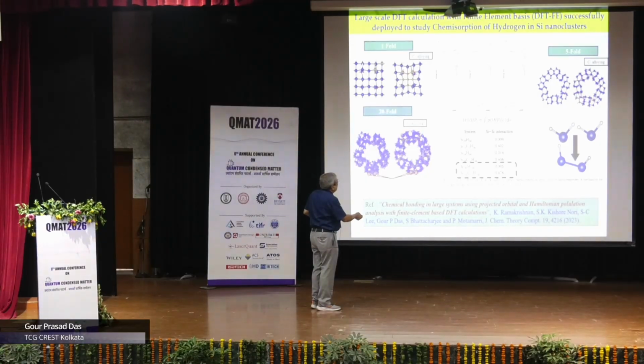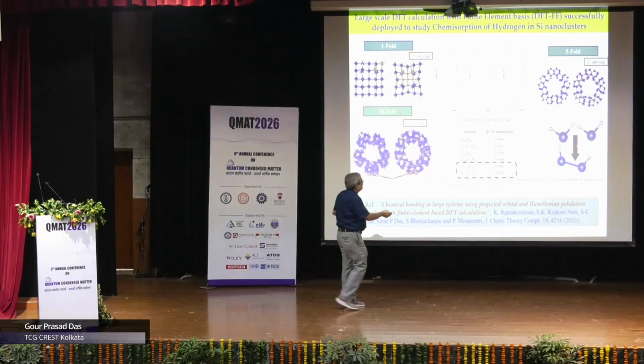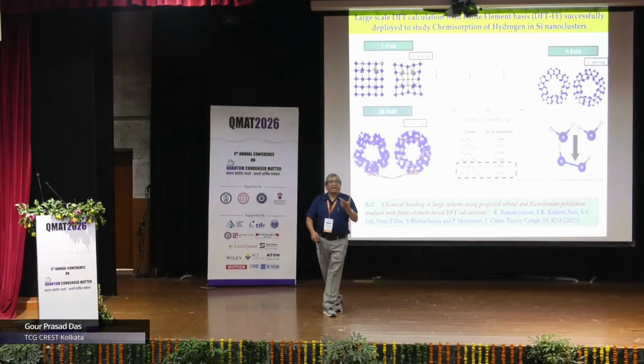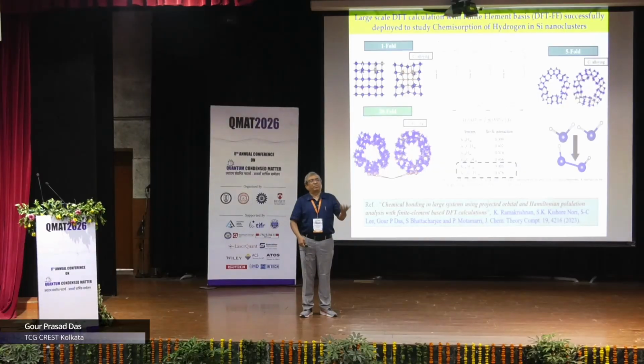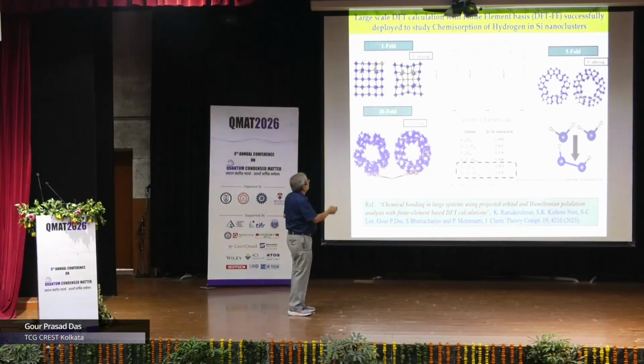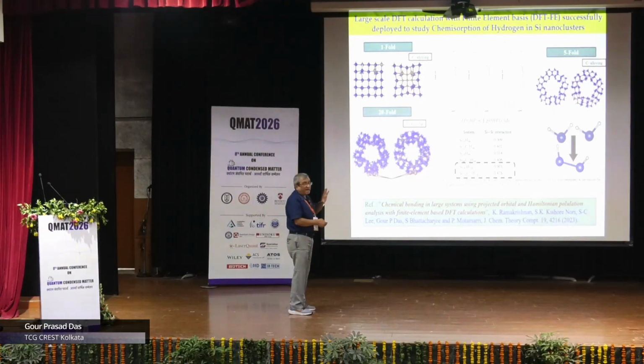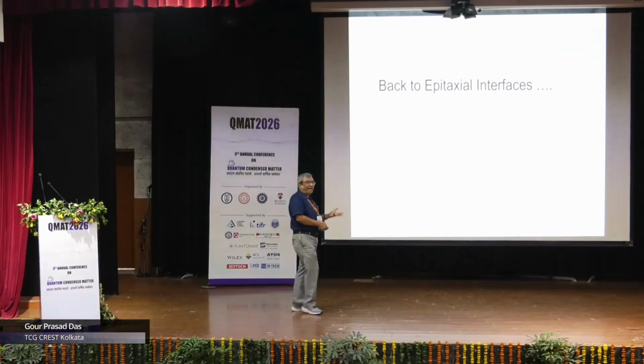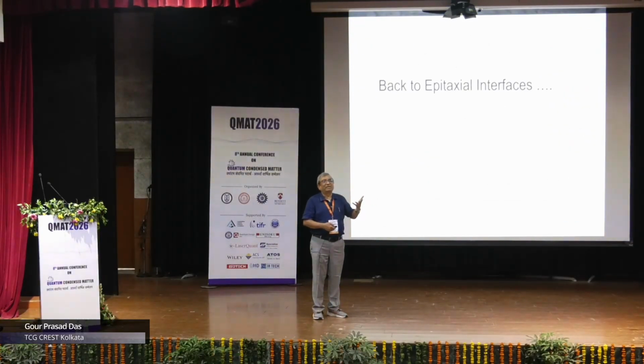It's huge. And if you do that, then we really find that the hydrogen dimerization is helped. And unless the hydrogens dimerize, we cannot use it for the purpose of hydrogen storage. Remember that in hydrogen storage, the hydrogen in a nascent H form is of no use. It has to be H2. So that was our aim. The original idea, I must say, was first given by Giulia Galli way back in 2004. But at that time, there was no way that a density functional calculation could be done at such a magnitude. We have done that.